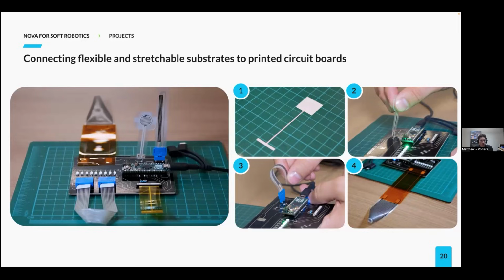Going in order, number one, the circuit highlights consists of a touch electrode, so that large square pad at the top, and then a trace leading down to the smaller contact region at the bottom. Once printed and cured, this substrate was covered with Kapton tape to insulate and stabilize the touch interface. When a finger or a conductive object approaches the pad, it increases the capacitance of that electrode relative to ground, and then it can be a readable output.